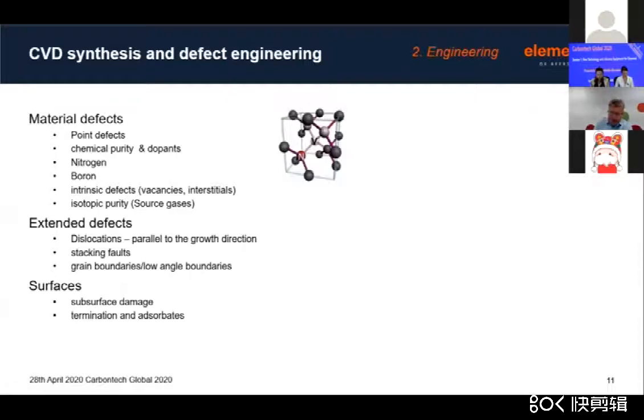And obviously you have point defects in diamond, such as chemical impurities and dopants substituted into the lattice, such as nitrogen, and it's the nitrogen vacancy complex that gives rise to the quantum optical properties and the pink color. You've also got extended defects such as dislocations and stacking faults, and then these can be quite a problem in CVD diamond because unlike many other semiconductor materials, you can't anneal them afterwards to eliminate fully these extended defects.